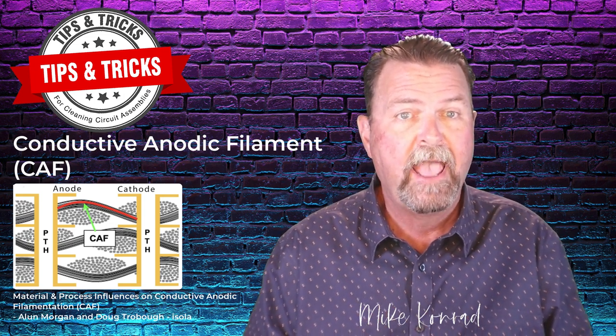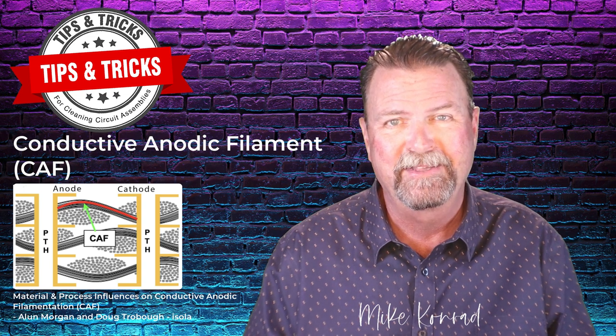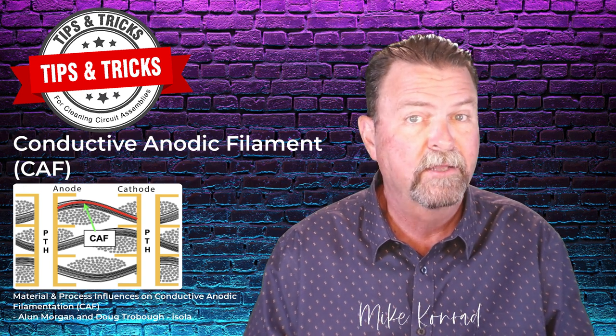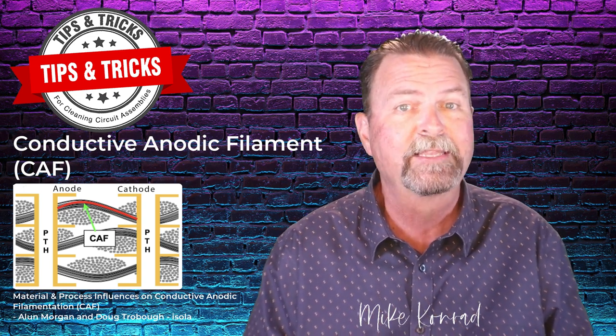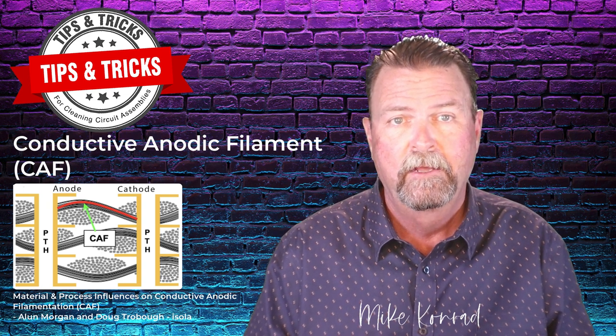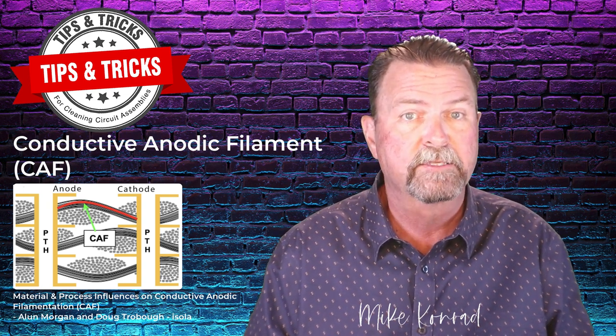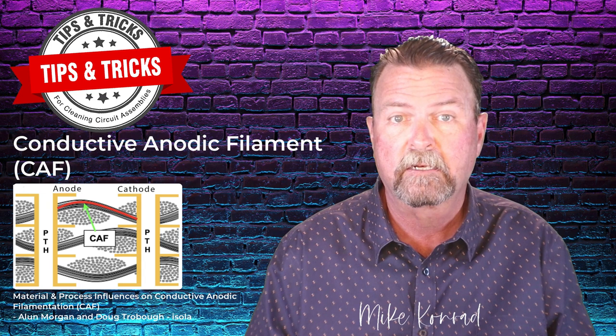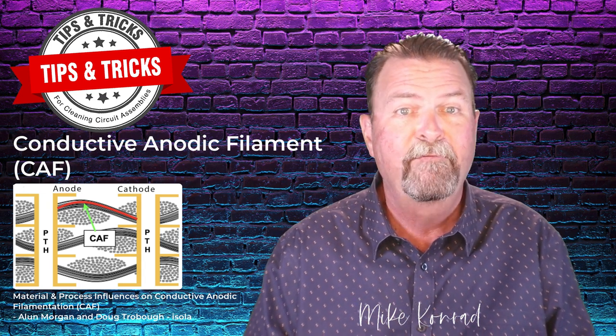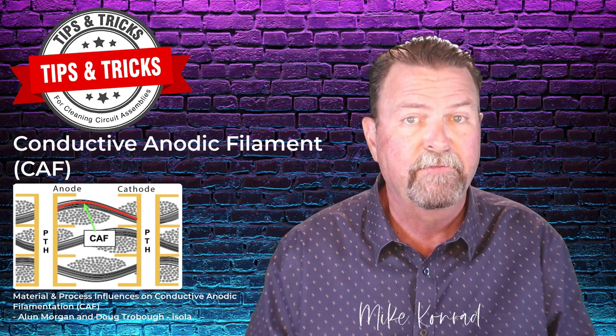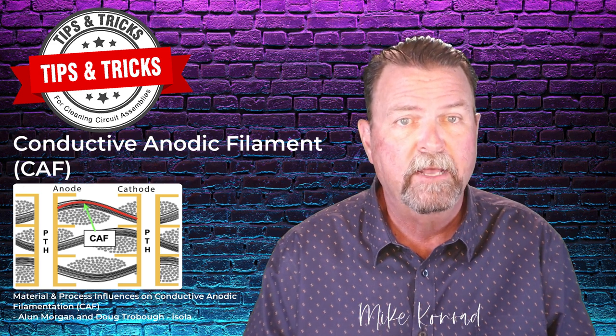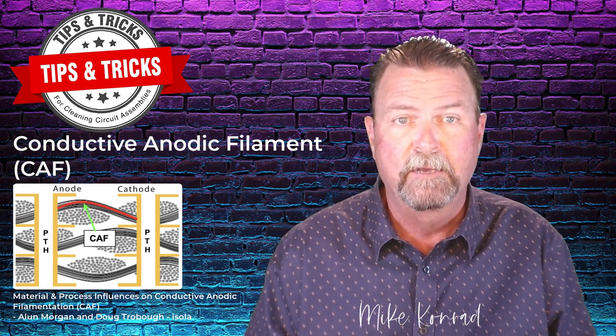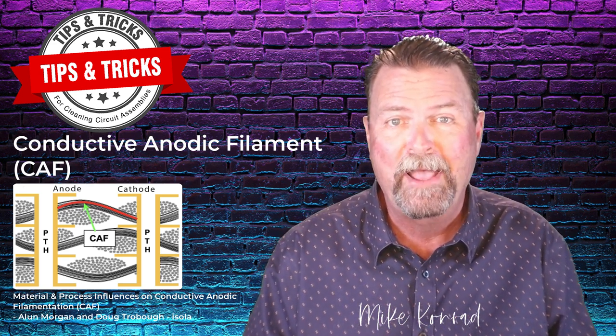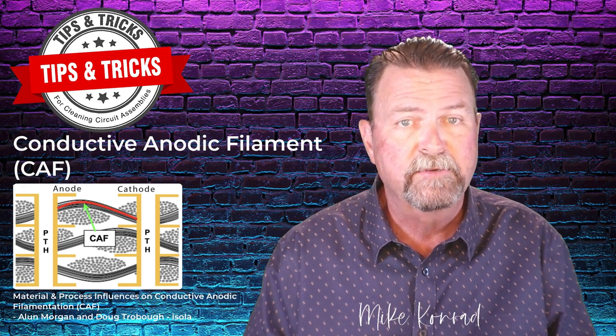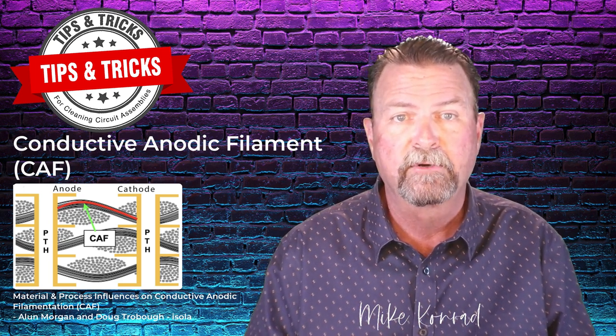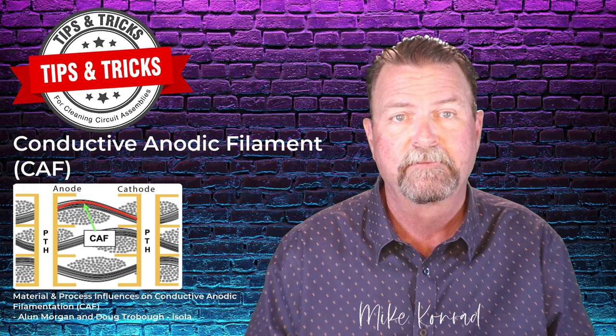I like to refer to CAF as a subterranean ECM event, as it occurs not on the surface of the assembly, but between the layers of the assembly. While surface-level ECM requires three elements: electrical bias, conductive residue, and moisture, a fourth element is required for CAF. There must be a pathway. On the surface of the assembly, the entire assembly is a pathway. Between the layers of the board, pathways are normally created during the board fabrication process.